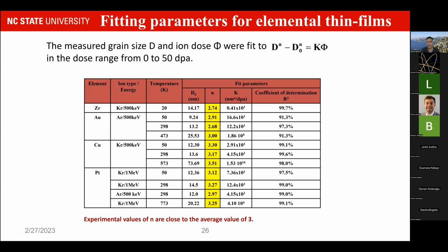What we observed was that regardless of the material, the N exponent was close to 3. So that had to be something that the mechanism of grain growth under irradiation is responsible for. But what we also observe is that the K parameter, in contrast, varied with the material, but also with the temperature and the irradiation conditions as well, whether we were using argon or krypton. So in the end, the experimental observation allowed us to make those two major conclusions.